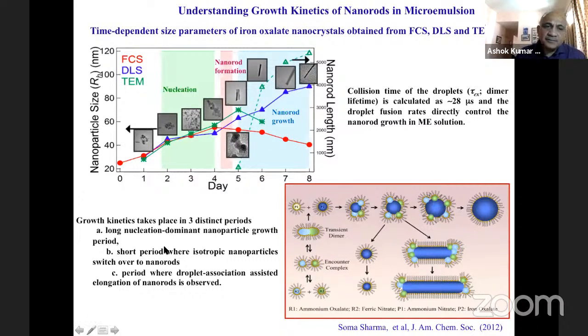When you analyze, you can watch that we mixed reverse micelles with Fe iron ions and oxalate ions, two droplets, and mixed them, and we are following using FCS. Then you can see that nanoparticle growth occurs, and this is a slow reaction actually. It takes some days, and then you get particles of different size, and the red dots show you the FCS data, and you can see that the growth continues. But however, after some time, the growth you don't see, because in FCS you cannot see large particles. When the particle has grown beyond a certain size, the data shows only some bare droplets.